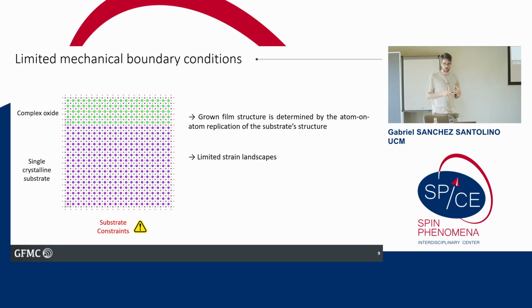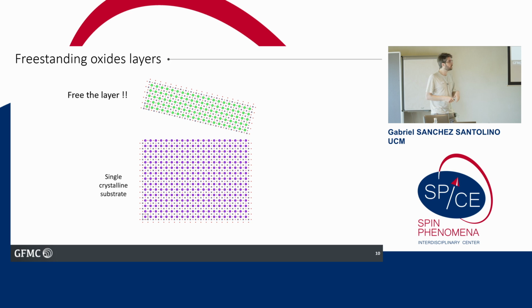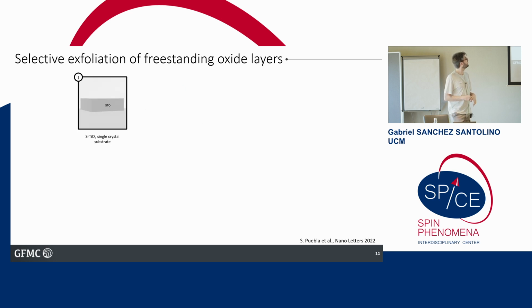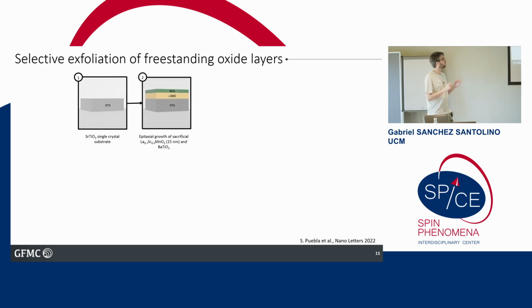So our idea was to get rid of these constraints by freeing the layer. So this is what we did. We grow the epitaxial layers and then we delaminate the layer, and now we can play with it and create different strain landscapes. To do this, we are going to use our single crystalline substrate, strontium titanate, which is one of the most common substrates used for complex oxide growth. We are going to grow 2 layers. One is the lanthanum strontium manganate layer, and the other one is our ferroelectric barium titanate layer. And we are going to put PDMS or a polymer on top of the structure,